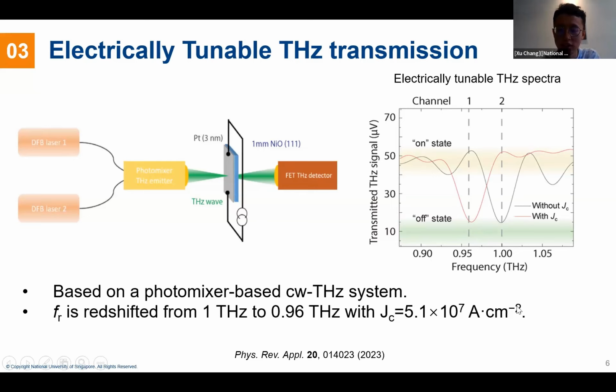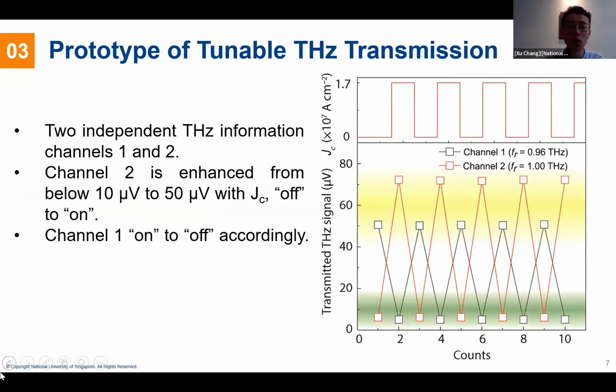So with injected current, we can actually tune the terahertz transmission spectrum. Based on this, we have developed a prototype of a tunable terahertz transmission. Here, if our injected current shows a square shape, we can tune these two channels of resonance frequency of 1 terahertz and 0.96 terahertz.